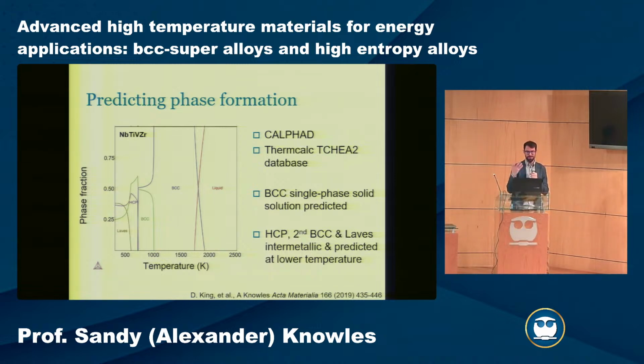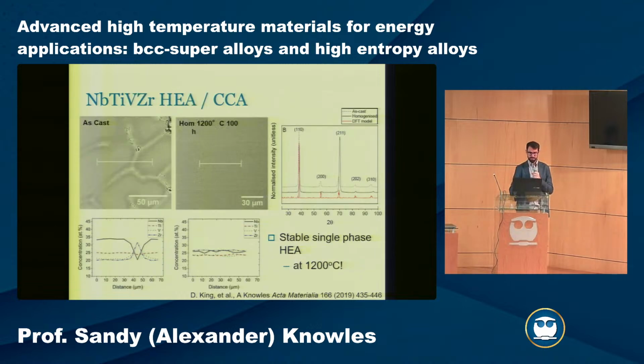But if you're pretty clever, you can use modeling methods and coding to try to loop CALPHAD into the discovery process. The key thing here is that at high temperature it's liquid, then it forms BCC as we go down in temperature, and then we have a combination of potentially second phase BCC, HCP, and this Laves phase intermetallic. So we wanted to see, well, we have this prediction, does that actually tie up to reality?